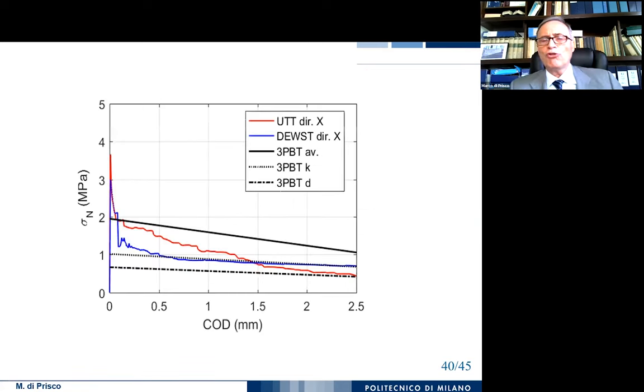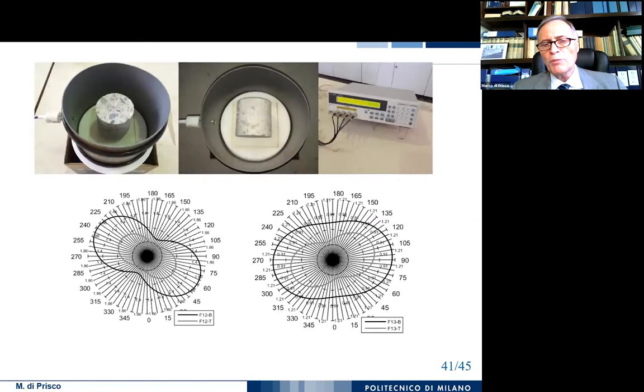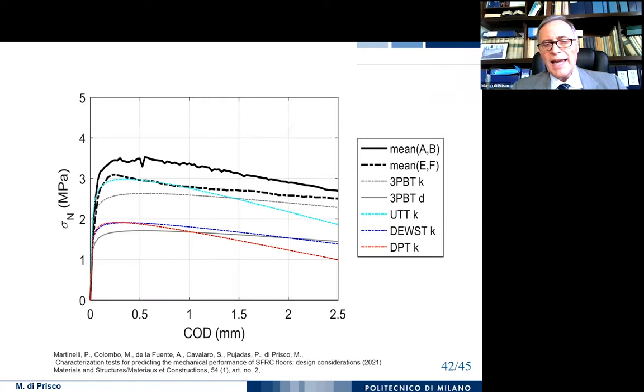Looking at the relationship with respect to the constitutive law extracted by the bending test, you can see that if you have this as an average value and you consider finally the characteristic or the design, and you compare with these curves obtained as the average of this acceptance test, you are always on the safe side. Please remember that when we core a material, we lose the contribution of some fibers, which remain cut by the coring. We can also evaluate by means of magnetic test the direction of the fibers in the specimen and in the core.